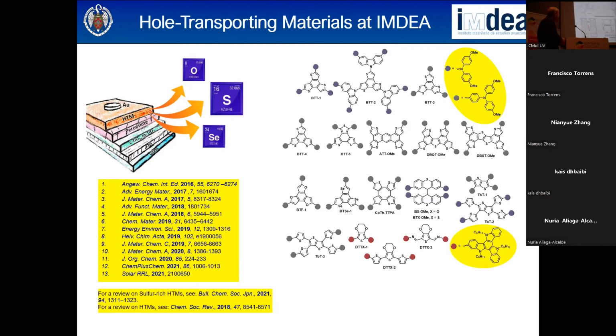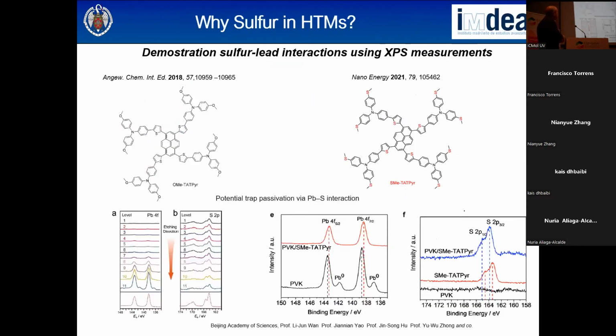So this is not our paper, but this is just a proof that with sulfur, these hole transporting materials are coming from the same Chinese group, but this is with oxygen on the periphery, this is sulfur. What they determine by XPS, X-ray photoelectron spectroscopy, is that this is the perovskite alone, okay? And this is the perovskite together with the hole transporting layer deposited on the top. And you can see that there is a small shift of the orbitals of the lead, and the same happened with those orbitals of sulfur. So that means that eventually you are having an interaction between the sulfur and lead atoms, okay? That is a very good indication for protecting and getting good results.